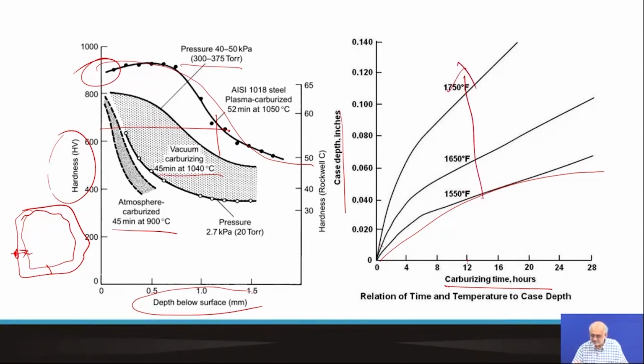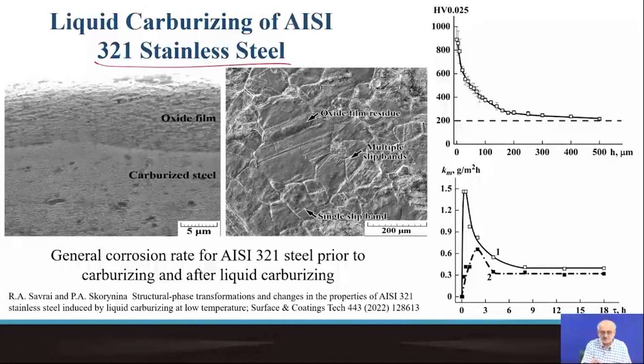So this is liquid carburizing in case of a particular stainless steel, which for various practical purposes is actually subjected to carburizing treatment. And when we do that, we also end up getting a higher amount of austenite on the surface because of carbon enrichment. But this oxide film is something which is an aftermath, which probably is created because of exposure to air. Typically, this is how the hardness varies with depth, we have already seen, and this is how again the depth varies with time.